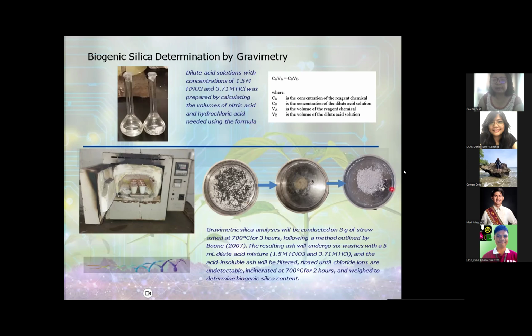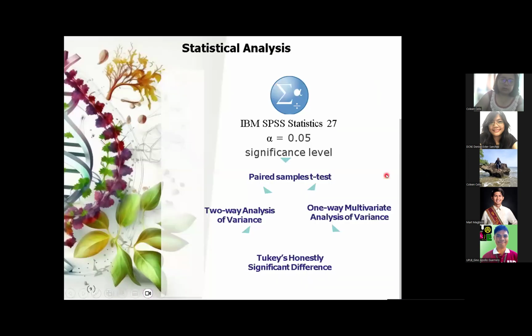So these are the steps. The first ashing, 700 degrees for 3 hours, is this. Then this is the dilute solution washing, where you can see the carbon content was reduced, because the black is carbonaceous material. And after that, this is the pure biogenic silica, the white ash.